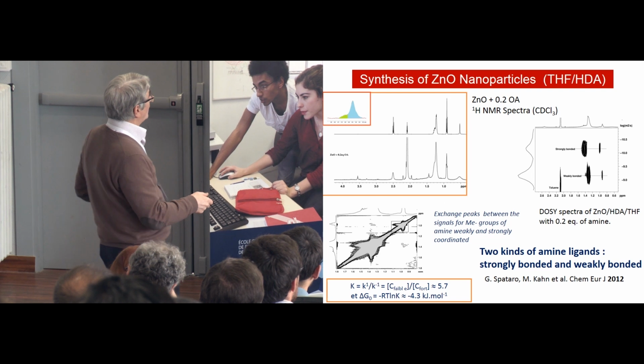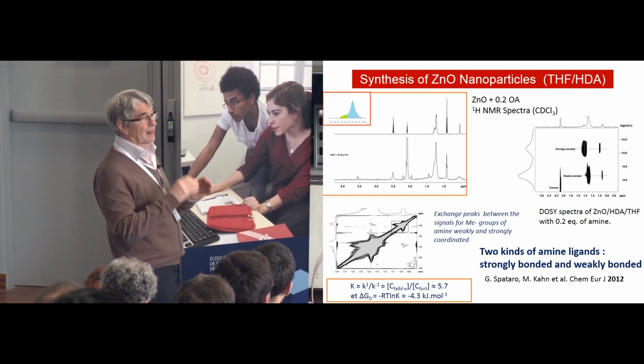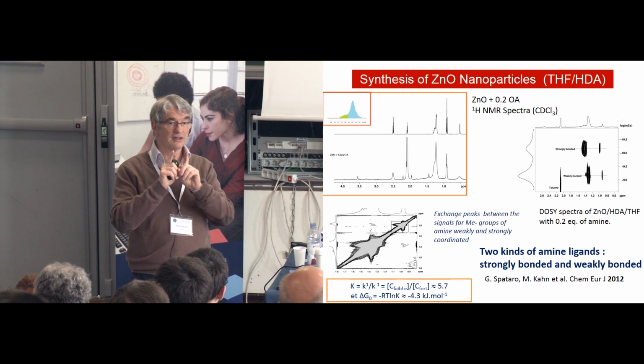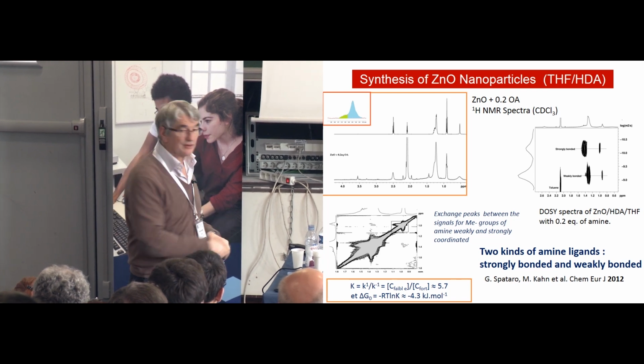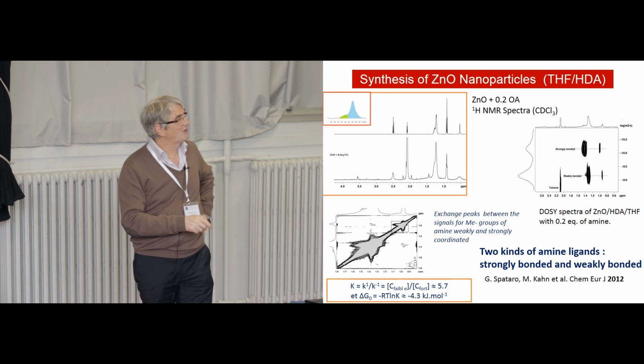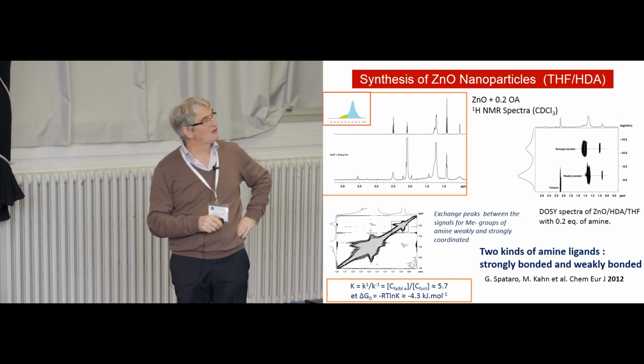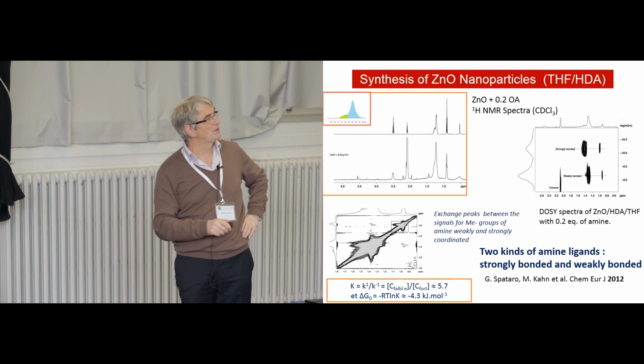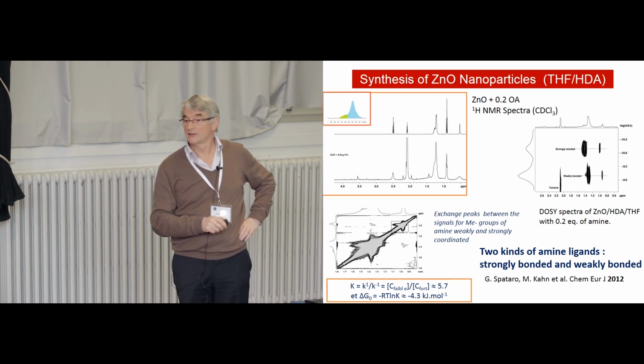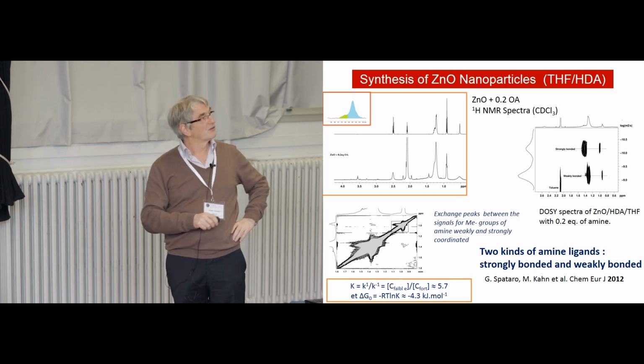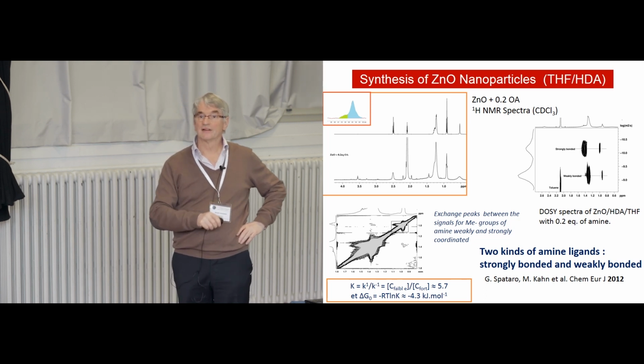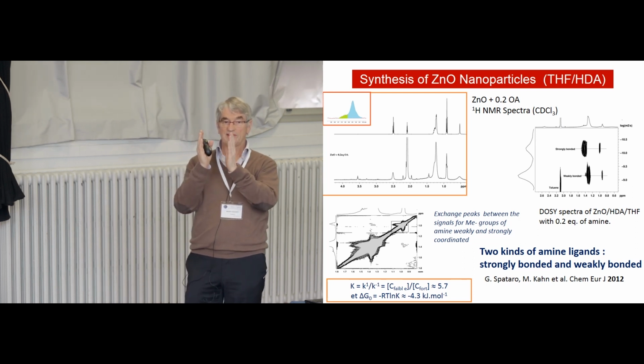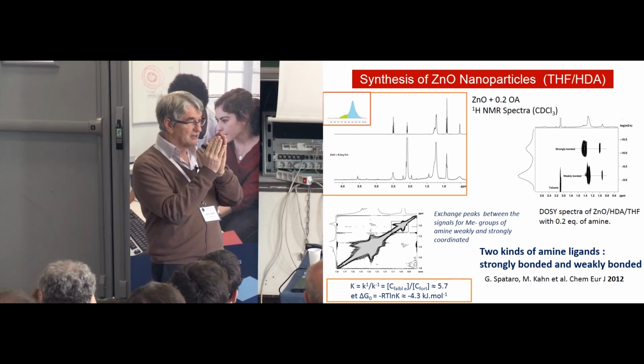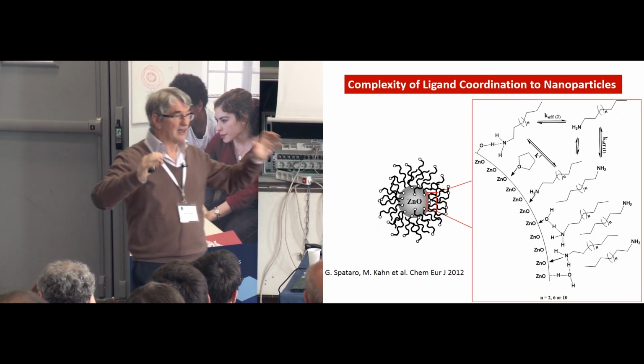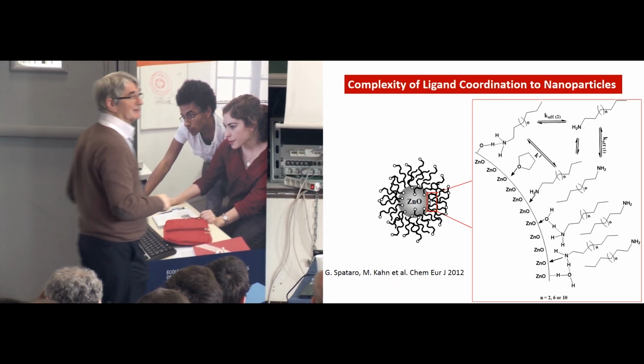And the other thing is that between two similar ligands, we can see if they see each other. And the funny thing we found is that they see each other, but not the way you would anticipate, because one is linked to ZnO, and the other one goes to the other direction. So there is a very complicated chemistry at the surface with interdigitated amine ligands. And we have seen that by the EXSY techniques.